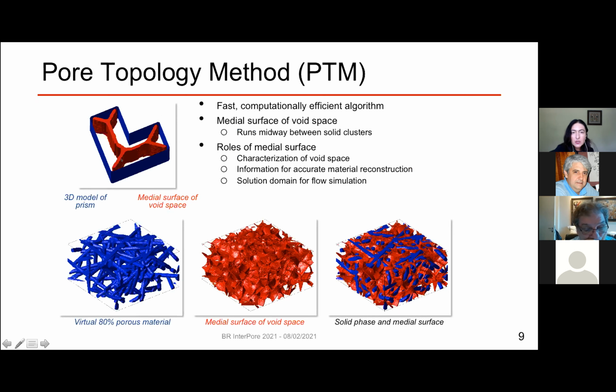And then this medial surface has multiple functions. It actually characterizes the void space. So we know what the void space looks like based on the shape of the surface. We can use it to reconstruct the material entirely because it holds all the information that we need about the material. And we also use it as a solution domain for flow simulation. So all simulations, all material calculations happen on this surface.